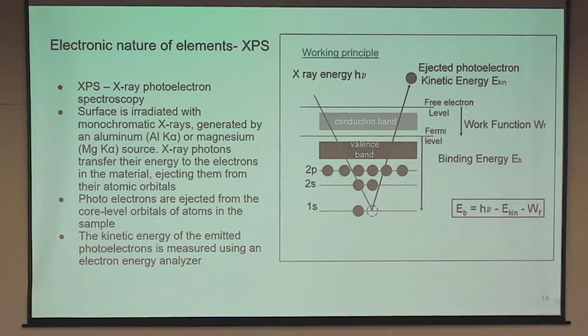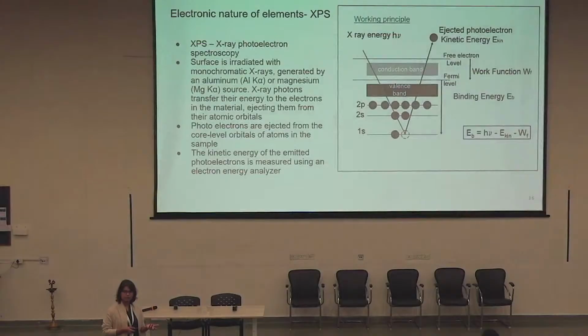In this technique, you basically measure the kinetic energy of the photoelectron that is ejected. You know the incident X-ray energy, and thereby you find out the binding energy of the electron. This binding energy is again a fingerprint of the element identity, and therefore you know what elements are present in your sample. Now I told you two things. First, I said this is very surface sensitive, right? How is this surface sensitive?